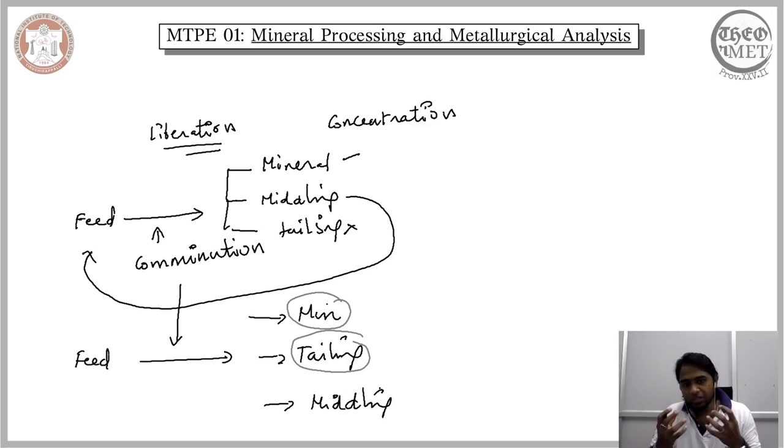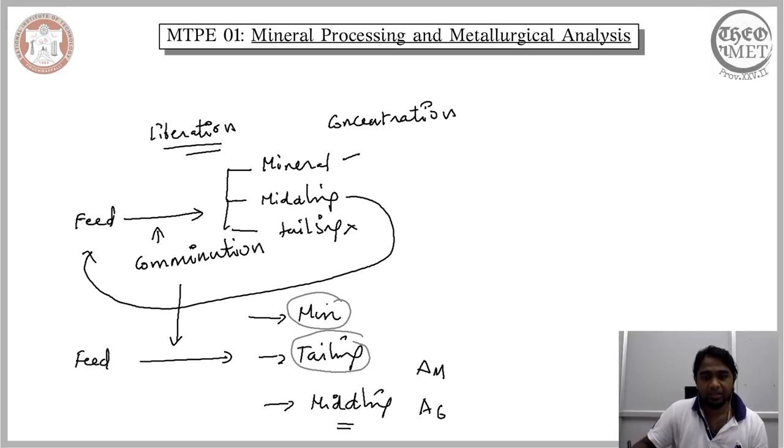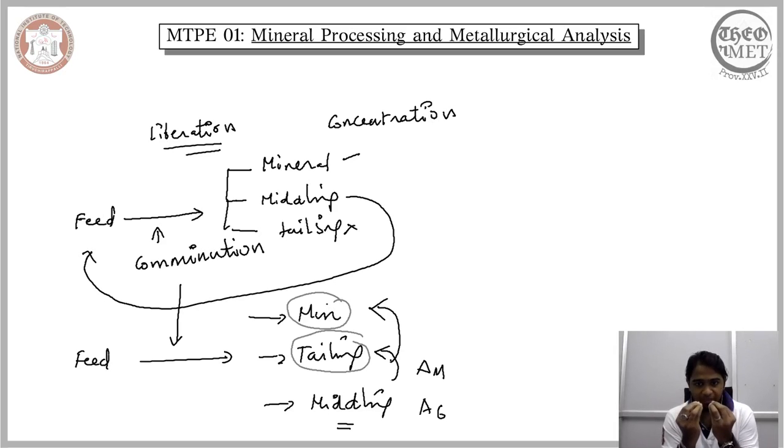Now it is not economically beneficial to impose second degree comminution on all of this middling. So we arrive at an acceptable degree of minerals or an acceptable degree of gangue. This helps us separate the middlings into free mineral particles and free tailing particles. So we agree upon a specific acceptable level of minerals and gangue present within the middling particles. Once this acceptable level is set, just by considering the middlings alone, we can categorize certain middlings as free particles, even though they are not exclusively comprised of minerals, because they comprise greater than or equal to the acceptable level of minerals.